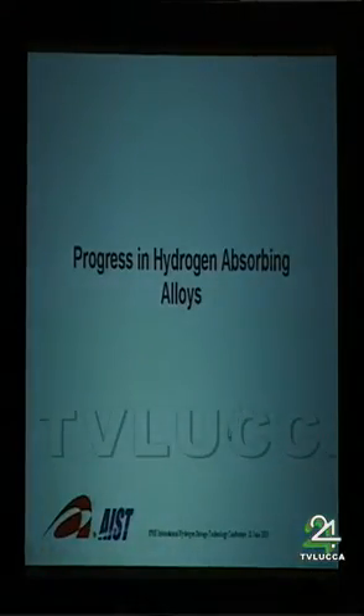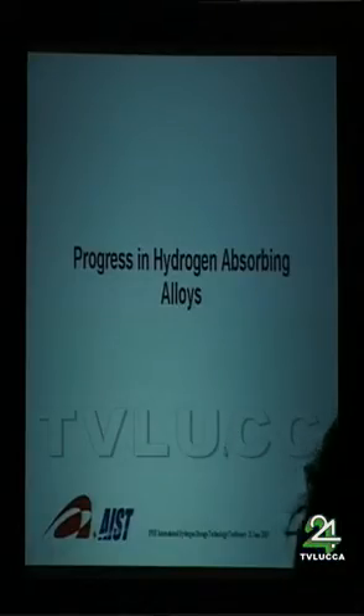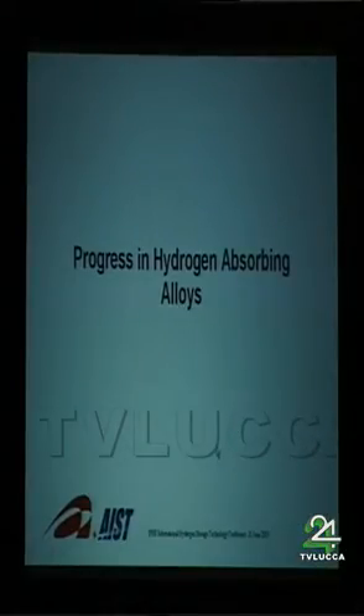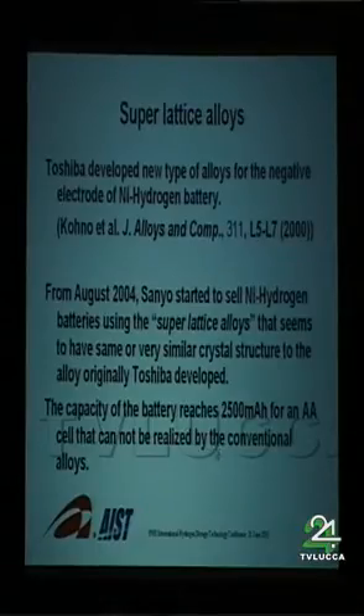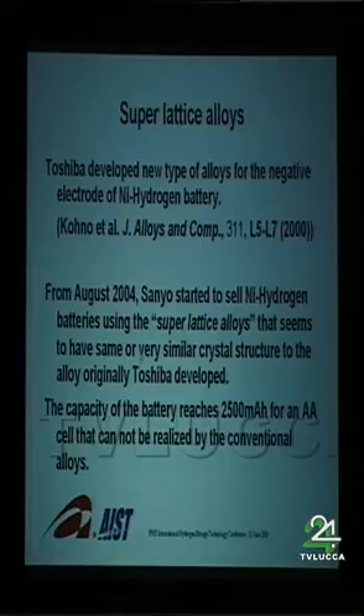And I'd like to move to a little more scientific part, and I'd like to introduce 2 examples carried out by my group on hydrogen absorbing alloys. One is the superlattice alloy. Toshiba developed a new type of alloy for the negative electrode of nickel hydrogen batteries. And last year, Sanyo started to sell nickel hydrogen batteries using this type of superlattice alloy. That seems to have the same or a very similar crystal structure to the alloy originally developed by Toshiba. The capacity of the battery reaches 2,500 mAh for one AA cell, which cannot be realized by conventional alloys.